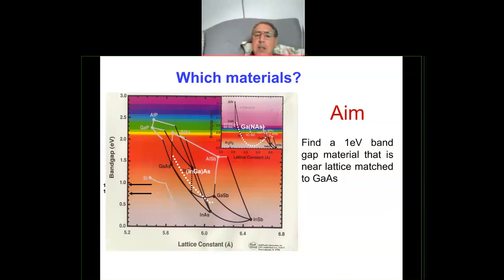But actually it doesn't. So what it does, the band gap actually decreases before it increases, because the energy band gap of gallium arsenide is 1.4 eV. So when you add nitrogen, a certain percentage, it actually goes down before it goes up. So this is how we're going to find this 1 eV material.